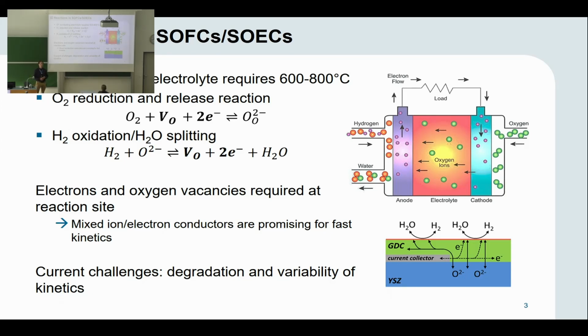However, there are some challenges, especially regarding the stability, the degradation rate of the electrodes, as well as the variability of nominally equally prepared electrodes and model cells due to small changes in the PLD parameters during the electrode preparation, or impurities or segregation effects. And yeah, I mainly want to tackle these segregation effects.